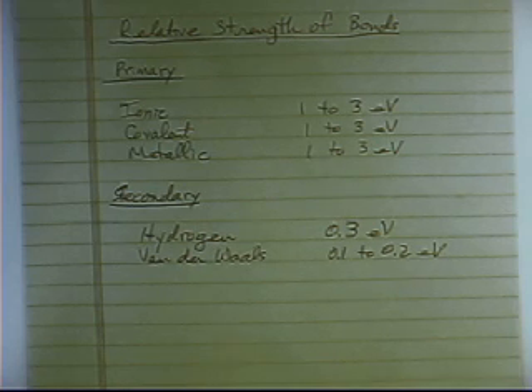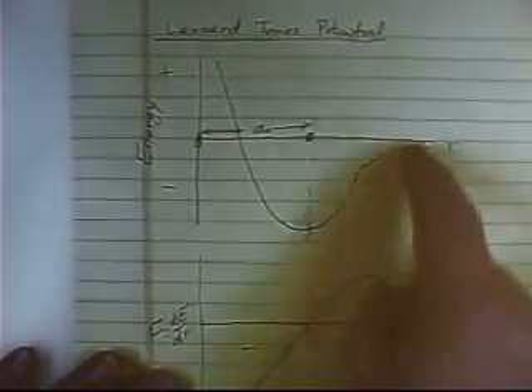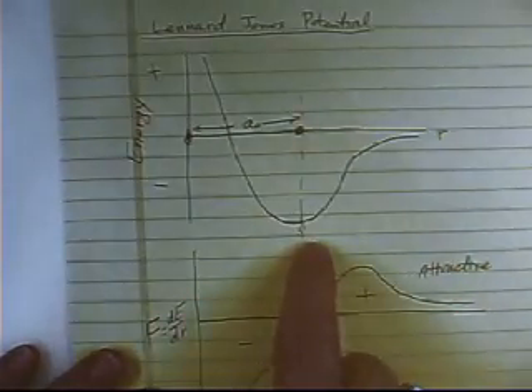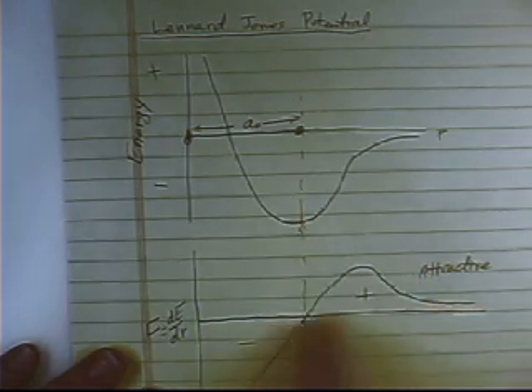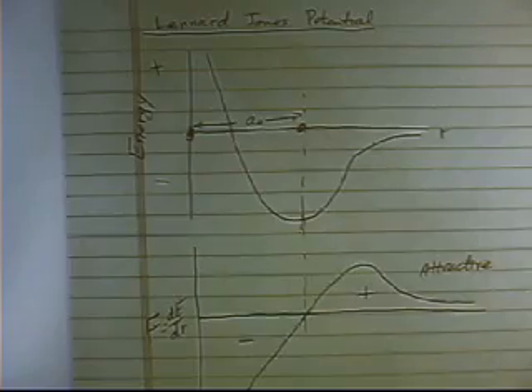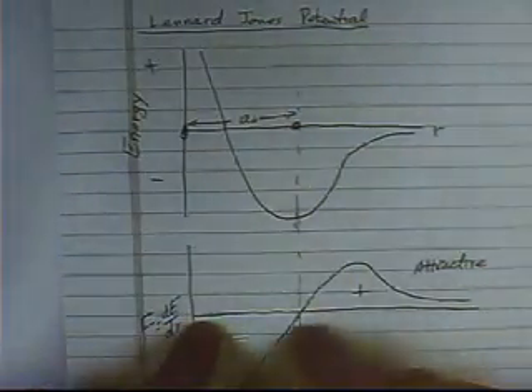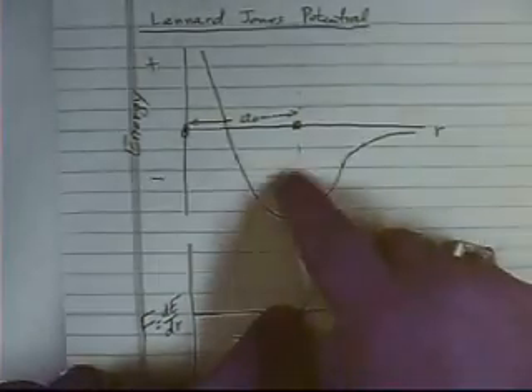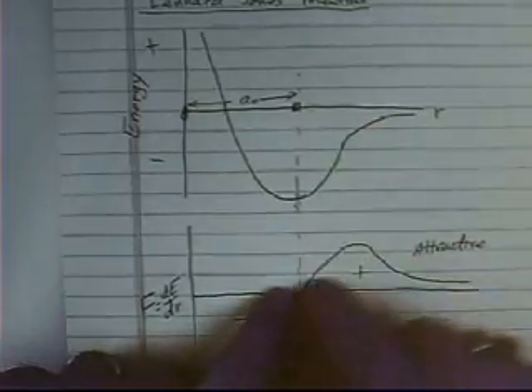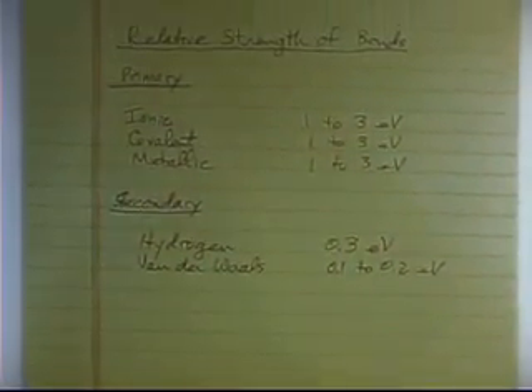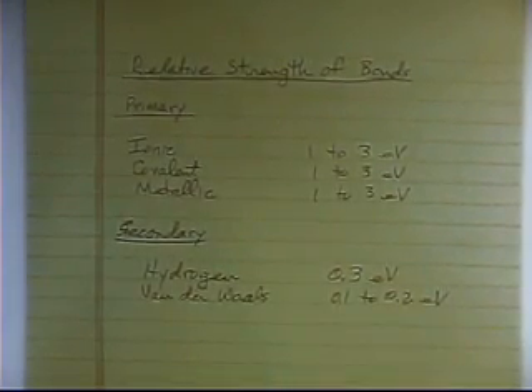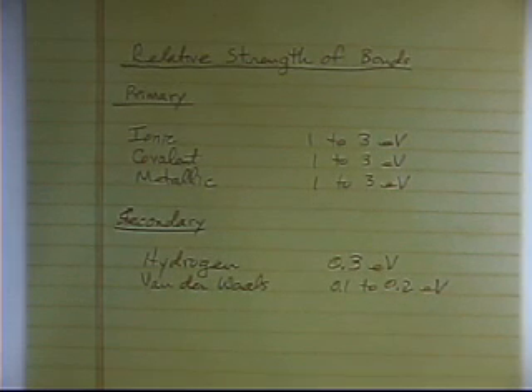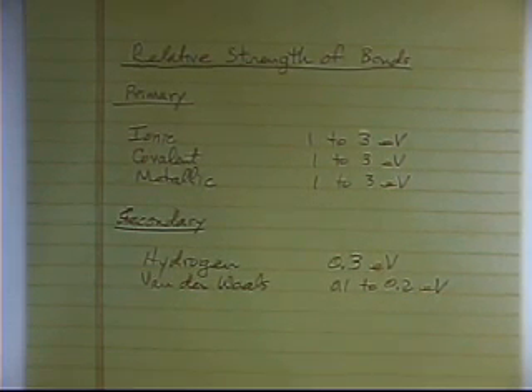Well, if that's the bond energy, which means that's essentially the depth of this potential well, you can integrate the force of attraction and figure out how much strength it would take to pull them apart, because you have to overcome this energy barrier. You have to add this much energy, force times distance, and you can integrate all that. How much strength do you think you'd have for a primary bond? Anybody have an idea? People actually measured this in the 1950s. They made single crystals of iron that had no dislocations, and they found that the strength of these iron whiskers was about 2 million psi.